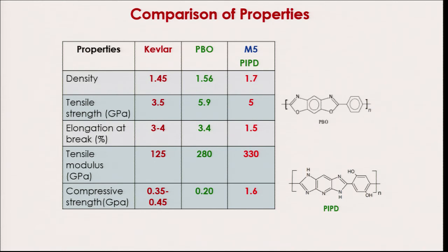PIPD has a hydroxyl group which is at a very suitable, appropriate position on the benzene ring. This hydroxyl group is able to form hydrogen bonding with the adjacent polymer chains on heat treatment, and it can lead to a 3-dimensional structure. That means, a structure in which there is 3D hydrogen bonding.